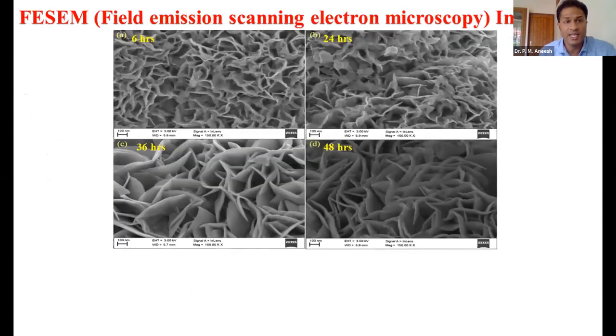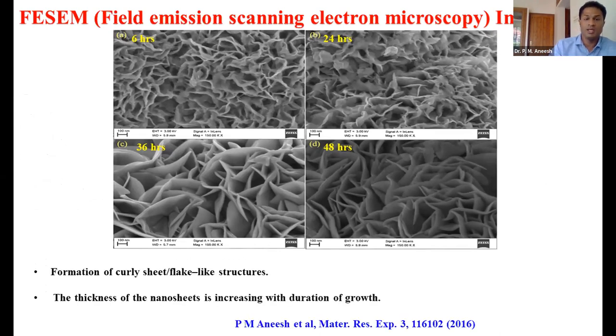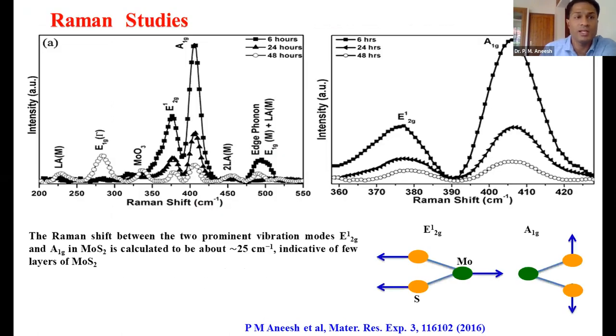And this is the scanning electron microscopic feature of this particular MoS2 sample. You can see that at 6 hours, 24 hours, 36 hours, and 48 hours, the size of the flakes increases with an increase in the hydrothermal time duration. Here we also studied the Raman spectra, and you can see there is a separation between A1g and E2g of around 25 cm⁻¹, which corresponds to a few-layer, 5-6 layer, MoS2 sample.